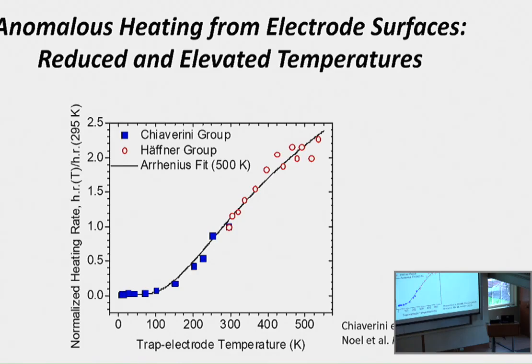But if you look at that temperature, that's way too low for surface diffusion. So that hints at the fact that there must be some other mechanism other than temperature that's causing whatever it is that's being driven on the surface. And my story is that it causes the work function to change and therefore gives rise to electric field noise. Okay? And there are those two references there.